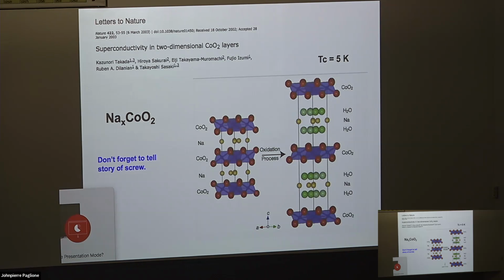A collaborator of ours was looking at it. We found this tiny, tiny little magnetic signal, and he ended up wasting a lot of time, because there was a screw that had fallen into that bottle of D2O. Just a screw in the bottom, a stainless steel screw. We didn't notice it. But that was enough to give a little magnetic signal to the watery superconductor. So that's how sensitive SQUIDs are, how careful you have to be.